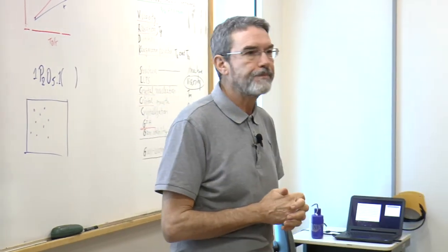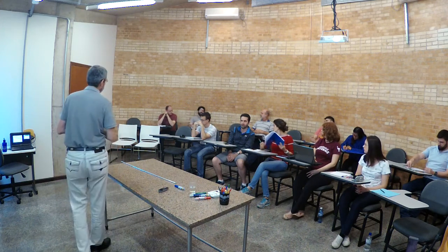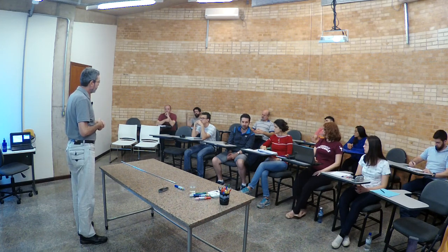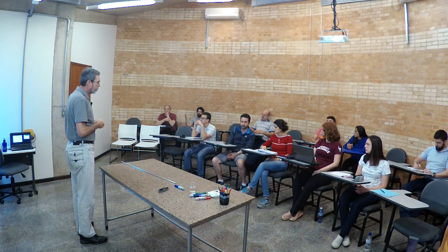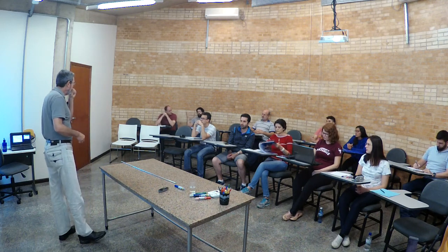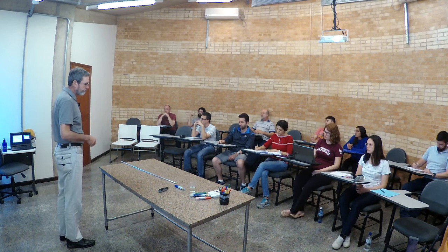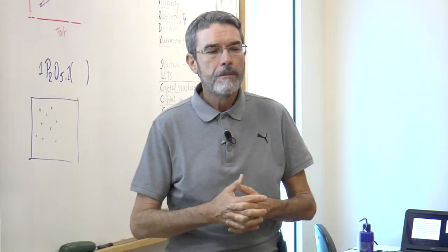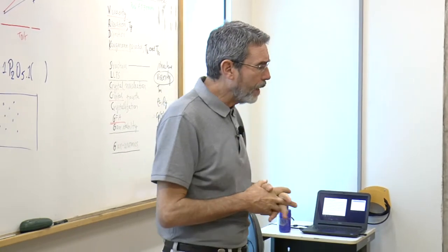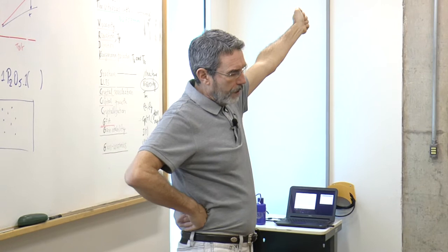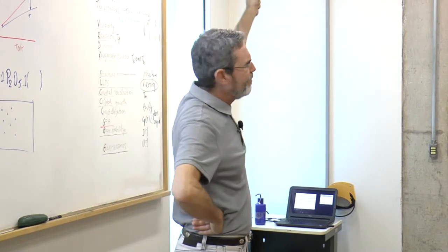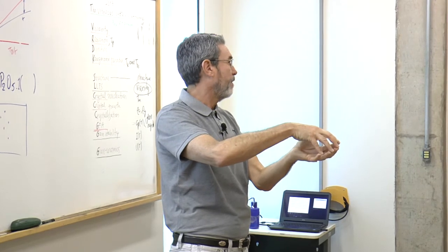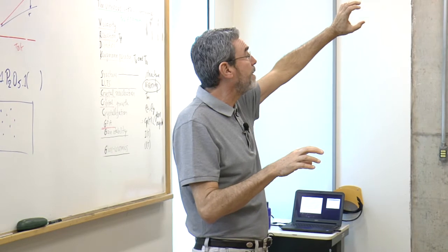Is there any question? I have a question. Yes. It's not about this, but it's about the fictive temperature and Tg. I was asking myself, how to measure the fictive temperature when it's different from Tg? There are ways to measure the fictive temperature. There's a very nice method produced by Moynihan, where you can, for instance, pull a fiber, quench a glass very fast, and then cast a very large piece of the same glass in a mold, which has a much lower cooling rate, so they must have very different fictive temperatures.